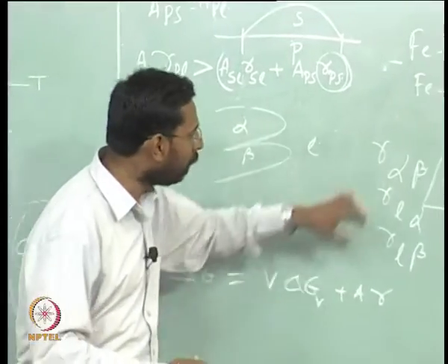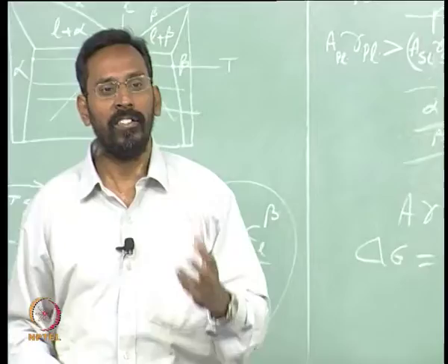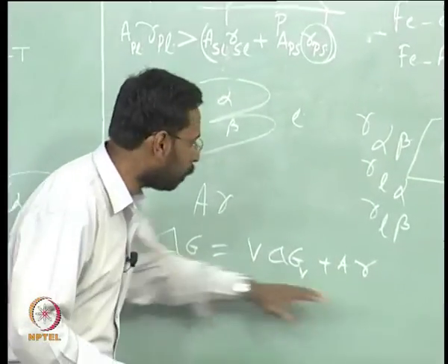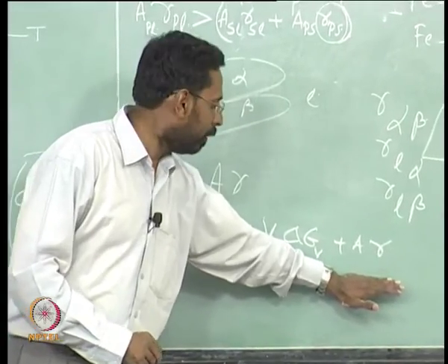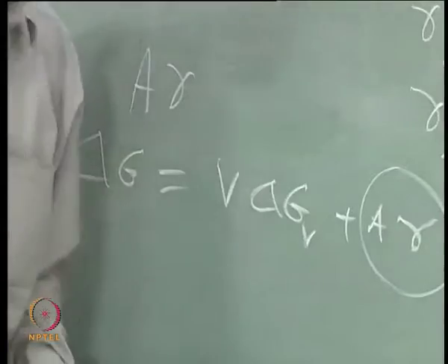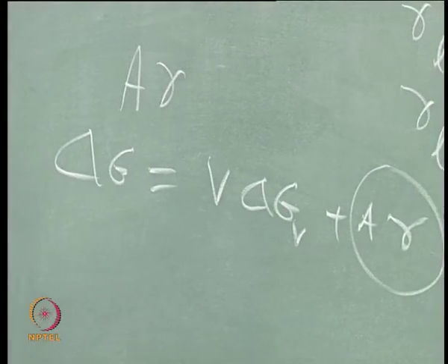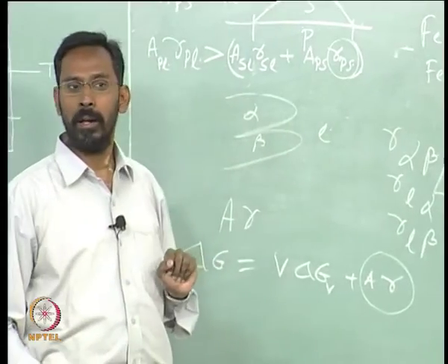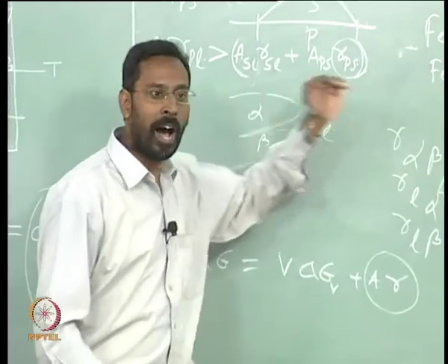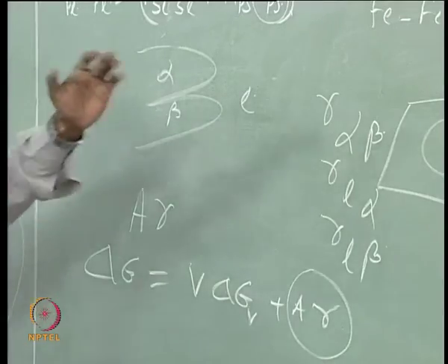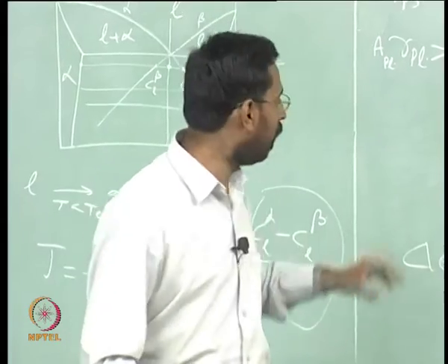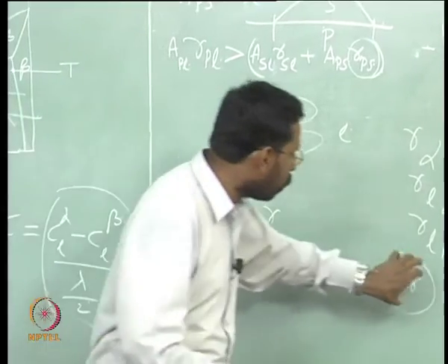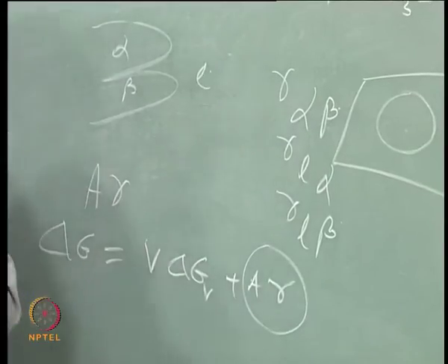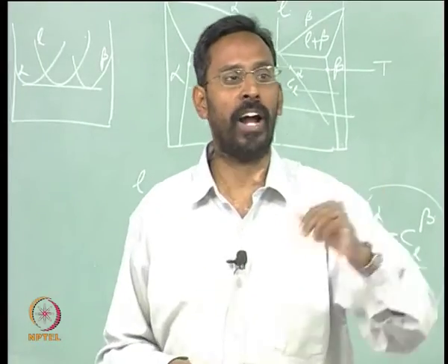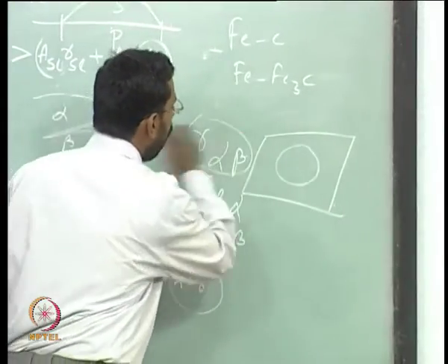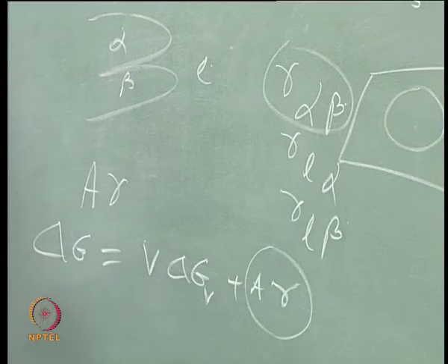Similarly, when you have three interfaces, the one with the lowest energy is preferred. For example, in a eutectic I split the total interfacial energy into three parts: A of alpha-beta into gamma of alpha-beta, plus A of alpha-liquid into gamma of alpha-liquid, plus A of beta-liquid into gamma of beta-liquid, since all three coexist. Out of these three parts, the system chooses whichever is lowest. That is why wherever you see a lamellar eutectic, it means the alpha-beta interfacial energy is the lowest.